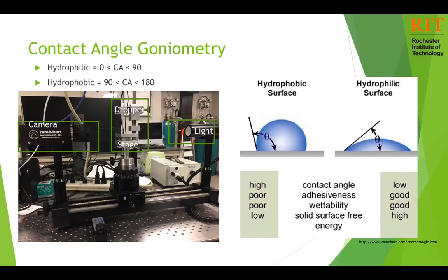As you can see in the figure to the right, a high contact angle above 90 degrees indicates a hydrophobic surface, and a low contact angle below 90 degrees indicates a hydrophilic surface. Contact angle is also related to adhesion, wettability, and surface free energy.